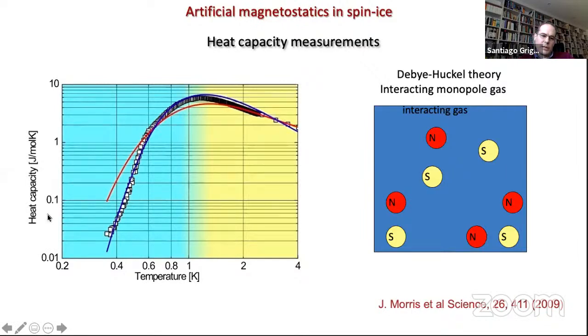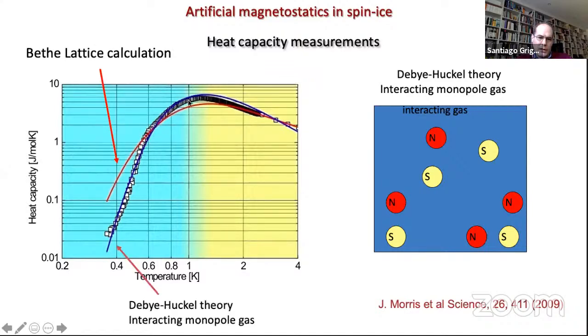So here, what I'm showing is the heat capacity as a function of temperature. The squares are the measurements we did, and the two lines correspond to two calculations. The first one is a Bethe lattice or Husimi-tree calculation. Essentially, this is assuming that the correlations die away very easily, and as expected, they work very well at high temperatures, but they don't work well at low temperatures. And the blue line here, if you can see it, corresponds to the Debye-Huckel theory. And you see that at low temperatures, when you expect this description to work, right? This description would only work if there's not too big a number of excitations. The description works very well.